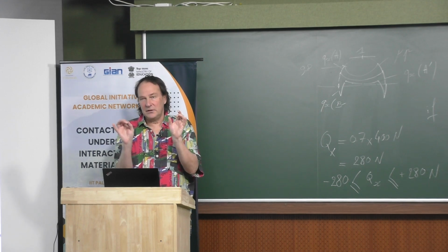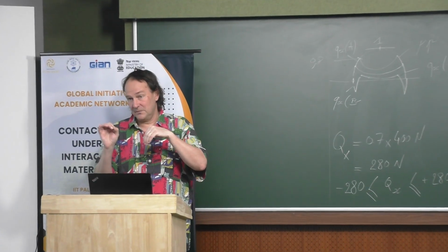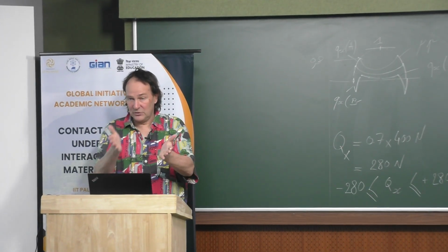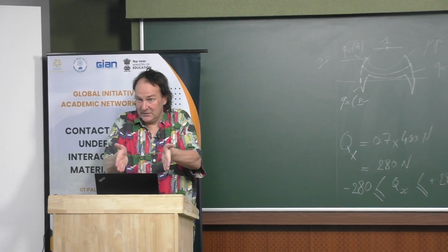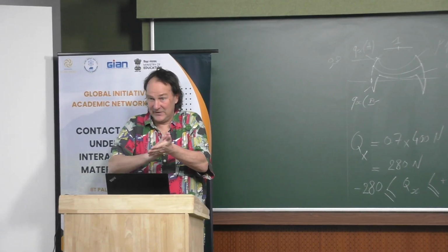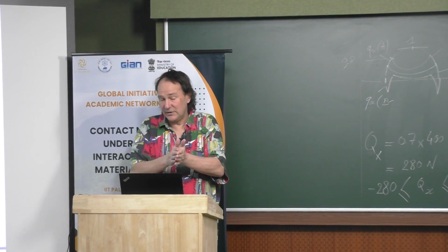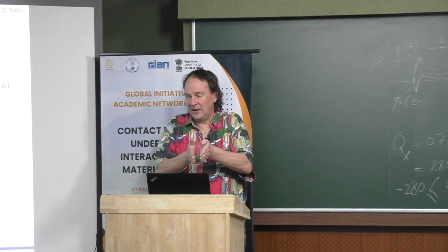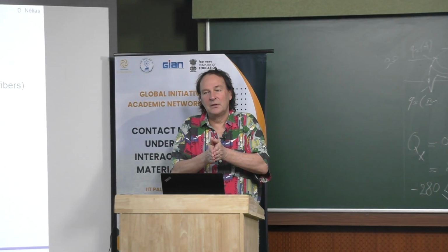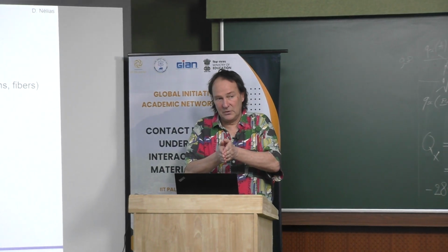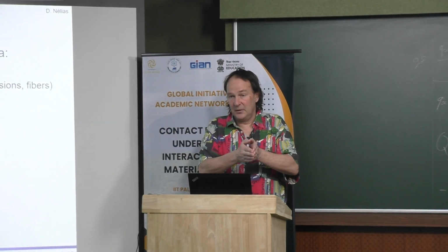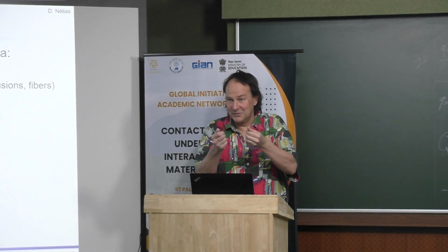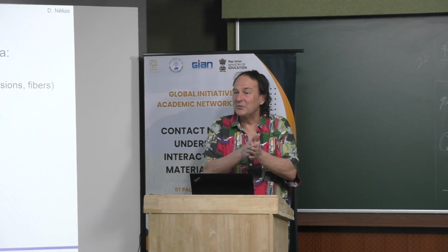Oxidation will modify the friction coefficient, and usually it should diminish it. For example, when you have the same metal, by affinity they stick to each other when they are very, very clean. But when you start to oxidize the surface, the affinity decreases and the friction coefficient will be lower. Then oxidation plays a very important role. The second one is debris. You can see debris as small balls that roll between the two surfaces, and this also diminishes the friction coefficient very significantly.